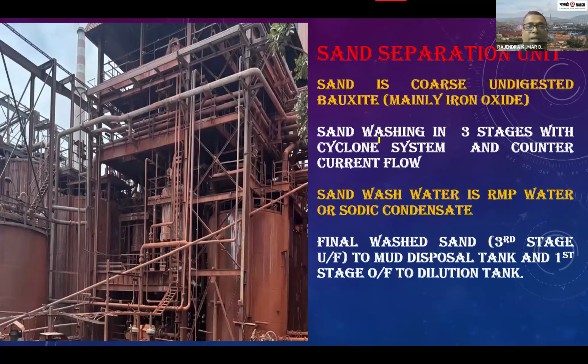This is the sand separation area. Sand is coarse undigested material, mainly due to the presence of iron oxide in the bauxite. Sand washing is in 3 stages with cyclone system and counter current flow system. Sand wash water is from RMP water or sodic condensate. Final wash sand, third stage. Underflow goes to the mud wash tank, disposal tank, and first and second overflow go to the dilution tank.